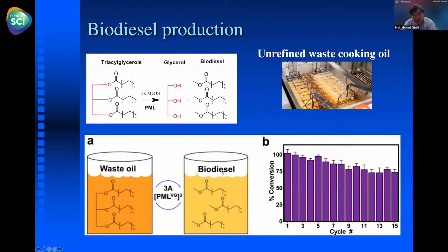And what's nice about the crystal is that you can recycle it. So here we go through 15 cycles, and you can see we're able to retain most of the activity over time. And I think most of this loss of activity is the loss of crystal in the emulsion between the oil and water layer. And if we can stop that loss, we can probably maintain that conversion much longer, and we're working on it.